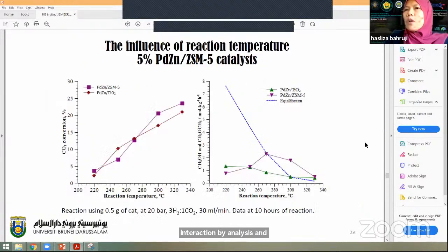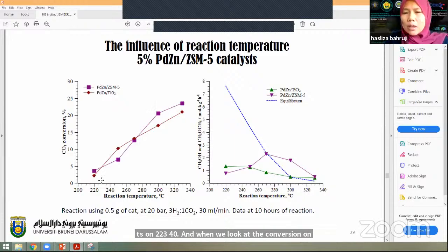Then we conduct our experiment from 220 up to 340, and when we look at the conversion on the palladium zinc on titania catalyst and palladium zinc on ZSM5 catalyst, the conversion is pretty much similar. So there's not much difference in the activity of the catalyst to convert CO2. But the main important thing is that by adding ZSM5 as a support, we actually managed to improve the selectivity of the catalyst to convert CO2 to oxygenated products, which is methanol and dimethyl ether.